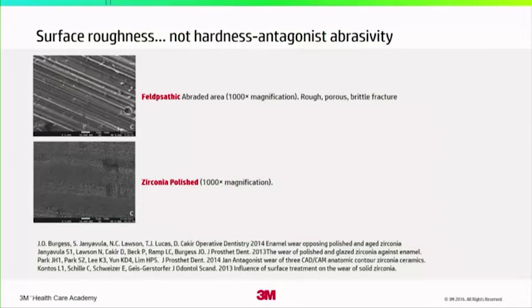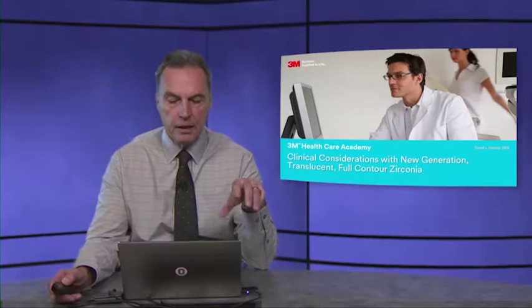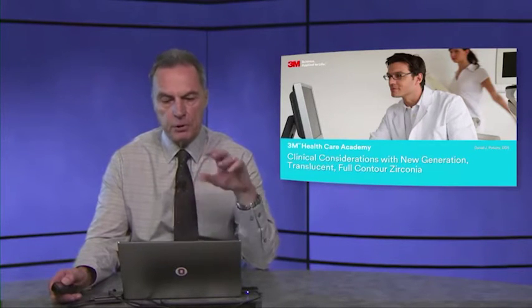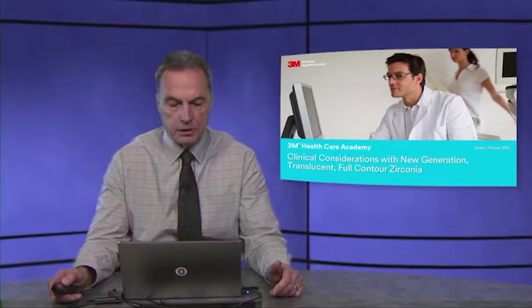And it's subject, in the wear principle, to what's called brittle fracture. What you're seeing is brittle fracture at a microscopic level that's producing roughness in the material itself. Zirconia, on the other hand, when it's polished, is very, very smooth. And even during wear, it maintains its smoothness owing to the very small crystalline size of the material and not having a glassy matrix with particles bound to it. You're going to get a very different wear principle compared to the feldspathic porcelain.